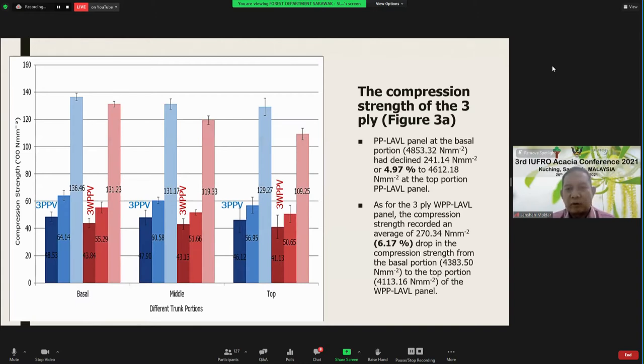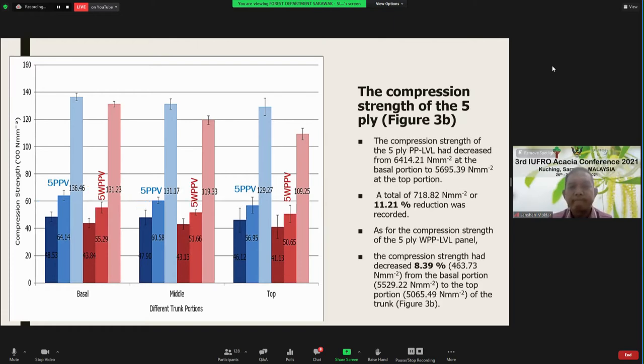So these are the compression strengths of the three-ply, for the basal portion, middle, and the top portion. The trend is almost similar, but compared to the without prepress, the prepressed veneer sample shows higher compression strength performance. The compression strength of the five-ply decreased from 6,000 at the basal portion to 5,000, a total reduction of around 700 that was recorded.